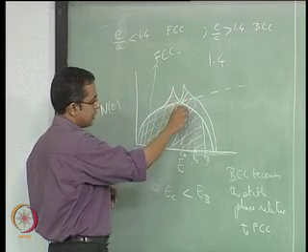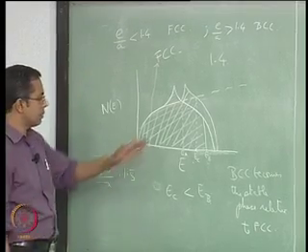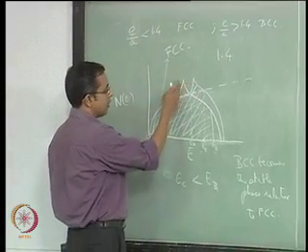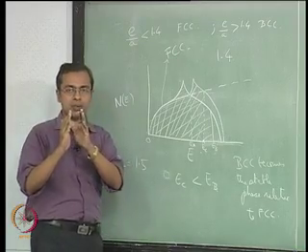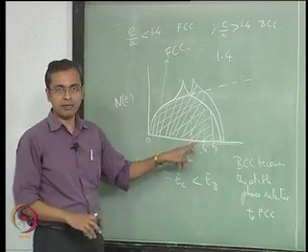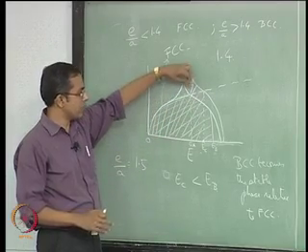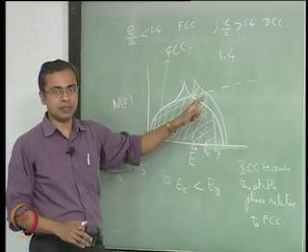So at some particular point here you will be able to get that 1.4, where it really depends on exactly where this curve is going up and exactly where that curve is coming down. There will be one particular point where both of them can hold the same amount of electrons at the same level of energy. After that, the additional electrons will be held at lower energy by one structure relative to the other structure, and therefore that structure becomes stable.